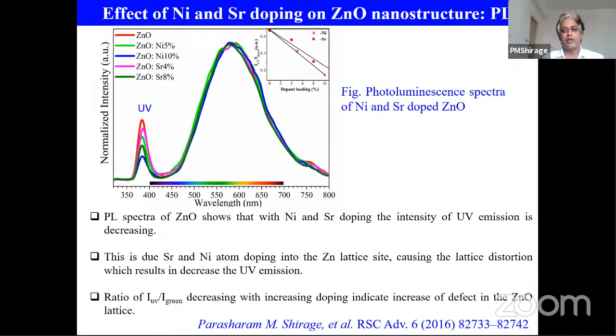Now another important piece of information. Once we prepare the material, we should know the defect levels, and photoluminescence will provide this important information: what type of defects are there, or whether defects are there or not, with doping and without doping. We measured this photoluminescence by exciting at 350 nm wavelength, from 350 to 800 nanometers. There are two regions, the UV region and the visible region.